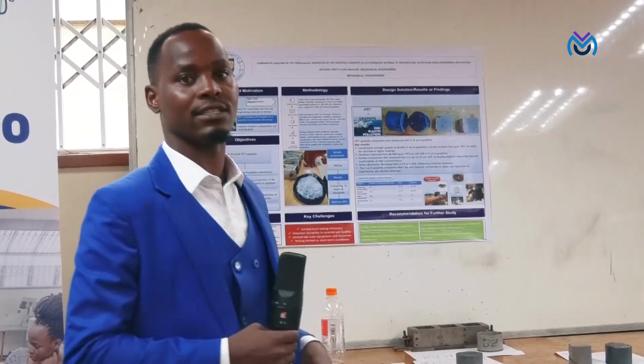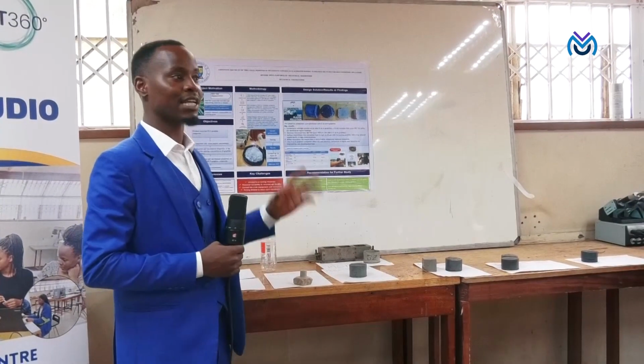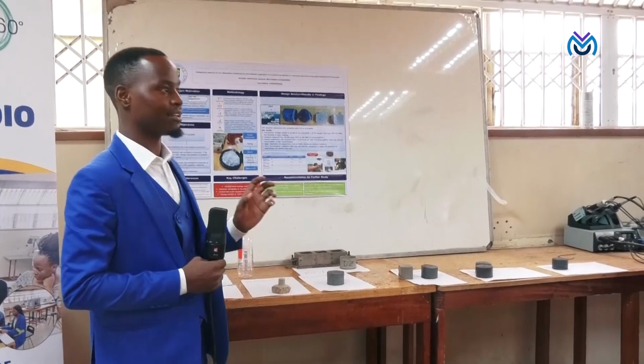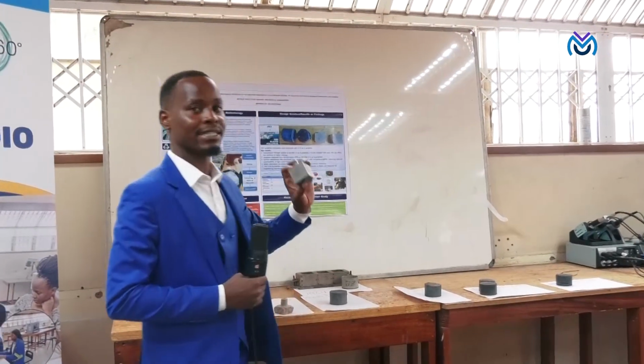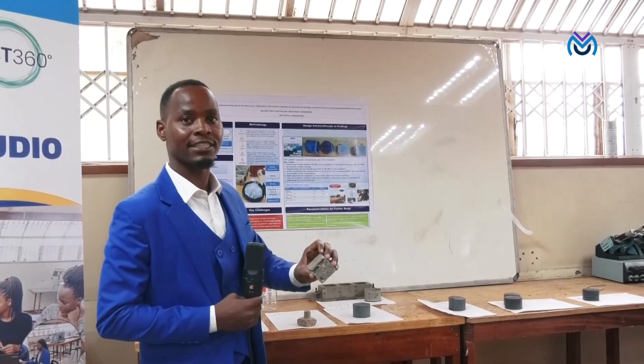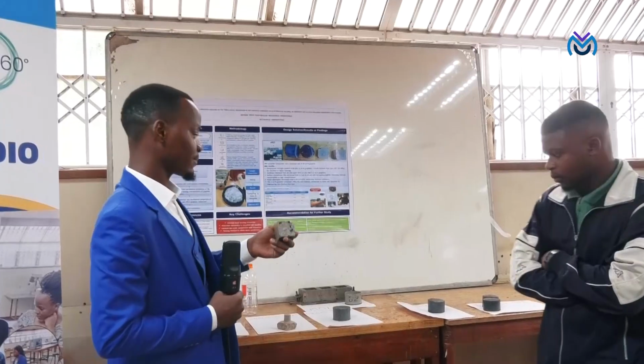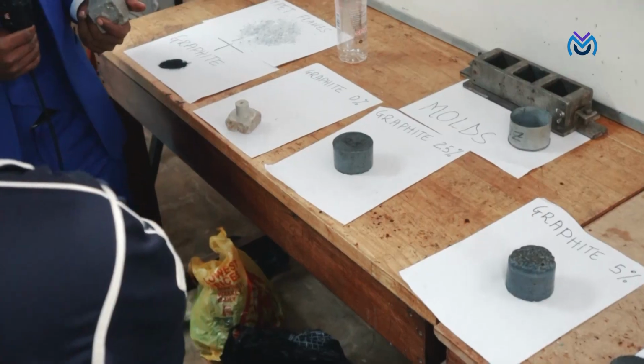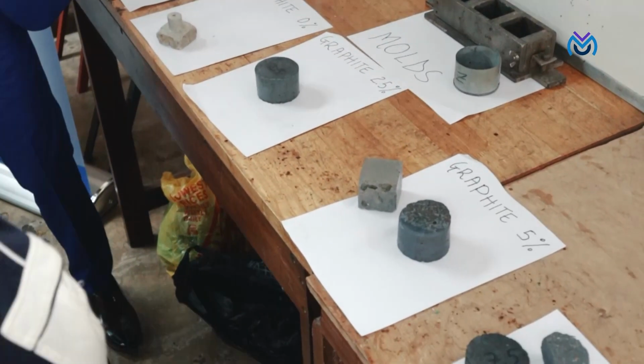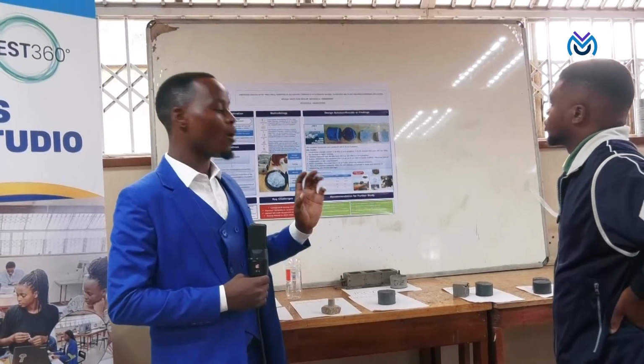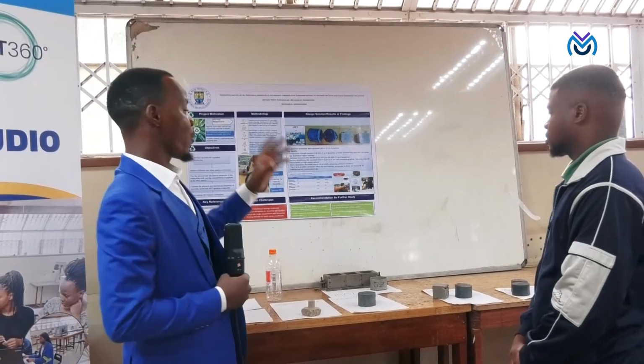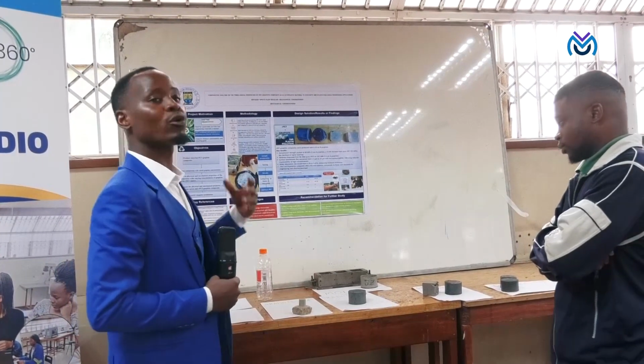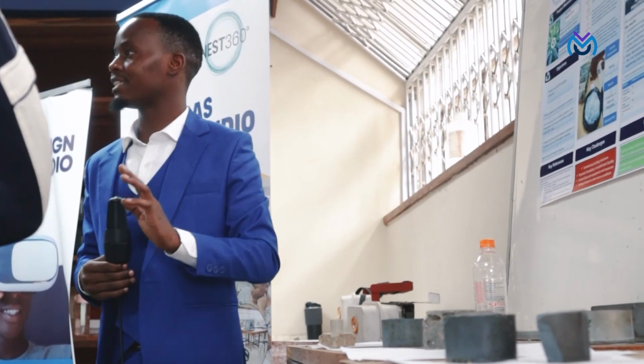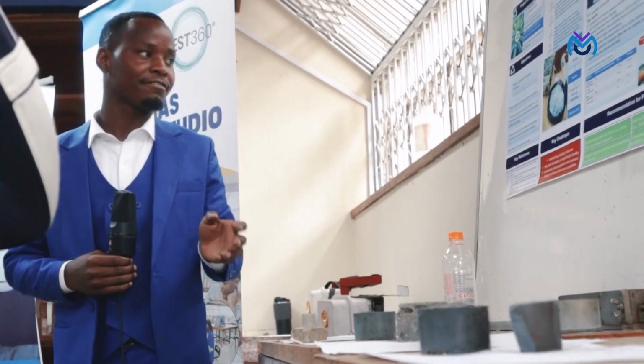So after all of these tests, we came up with a sample which has properties that mimic nylon and Vesconite. And that sample is this one, a sample with 5% graphite as well as 95% recycled polyethylene terephthalate. So how important is our project? After finding the optimum combination of graphite and RPET, we are now able to find an alternative material which we can use to replace nylon and Vesconite. And this alternative material is the one which has 5% graphite and 95% recycled polyethylene terephthalate.